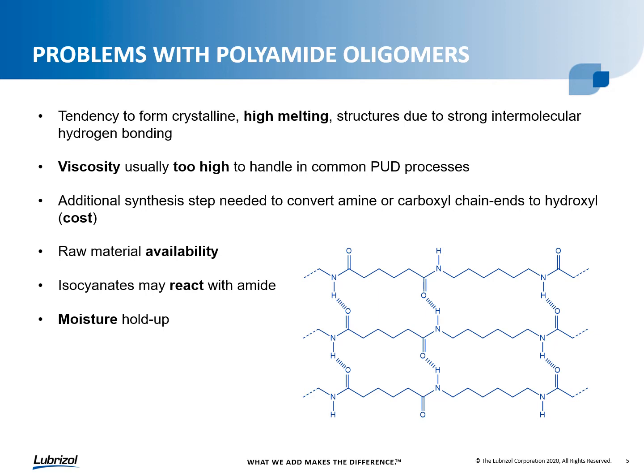Then you sometimes have additional synthesis steps required to convert the amine or the carboxyl chains to hydroxyls so that you have that OH group available to react with the NCO group on the isocyanate and form a urethane linkage. The other challenge is raw materials just aren't as readily available. And then you have the potential for isocyanates to react with the amide group. In making polyurethane dispersions, I was trying to minimize the side chain reactions, whether that's with water or in this case, the amide, that you have a reactive isocyanate that you're trying to minimize these side chain reactions that could lead to some undesirable byproducts in your product. And then the other challenge being potential for moisture holdup issues.